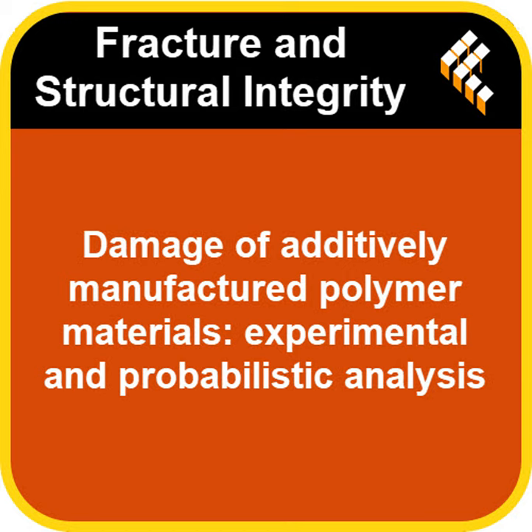But what happens when a part isn't perfect? What about those artificial cracks, the notches they introduced? Yes. This is where the study really gets into the damage analysis, the core of it. And the first big finding here was that any initial notch, even a really small one, significantly reduced the tensile strength compared to a perfect sample with no notch. Any notch. Any notch. And here's the crucial, perhaps slightly counterintuitive takeaway. The strength didn't just drop off a cliff once you had a crack. It decreased gradually as the notch size increased.